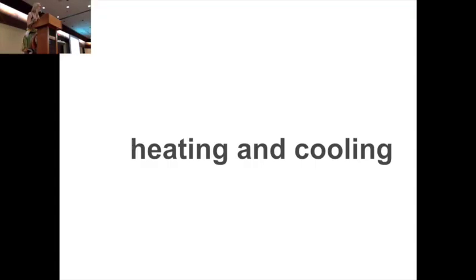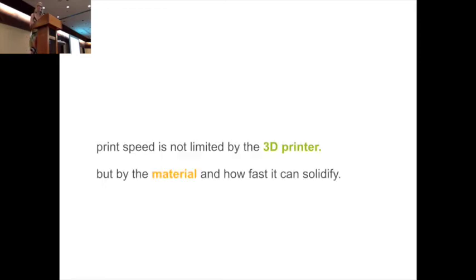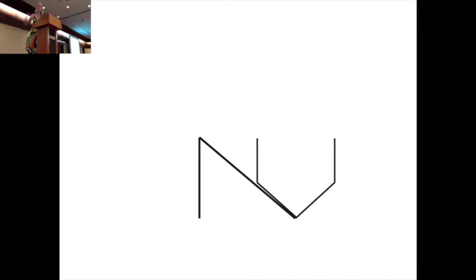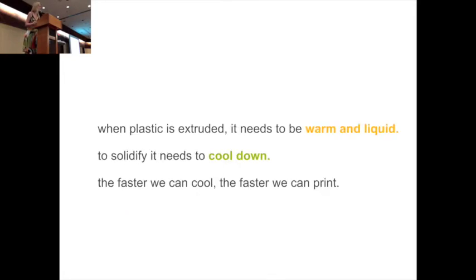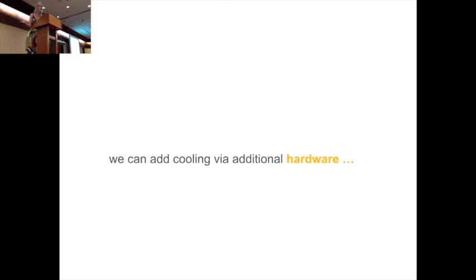And finally, the most important thing to make WirePrint work is to get the heating and the cooling right. The most important thing here to understand is that the print speed is not limited by the 3D printer itself but actually by the material and how fast it can solidify. Let's say you want to print this zigzag here and you print it full speed on your 3D printer. What you're very likely going to see is something like this, that the top corner actually deforms, which is certainly not what we want. The reason is that when the plastic is extruded it is actually warm and liquid. To solidify it needs to cool down, which means that the faster we can actually cool, the faster we can also print.